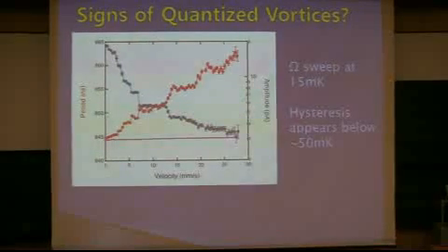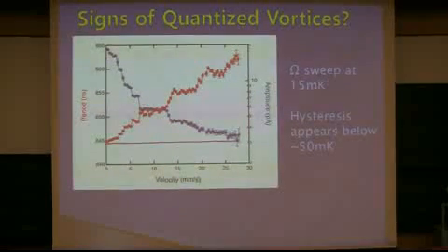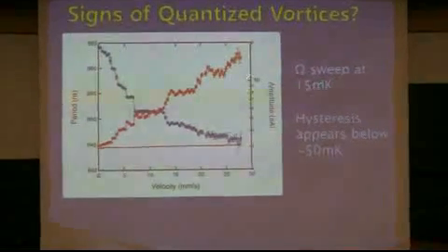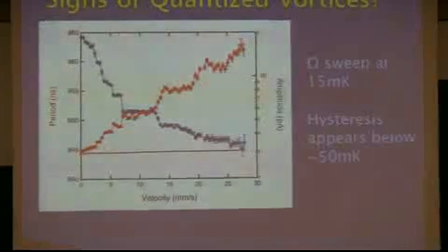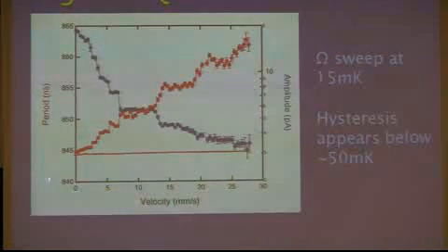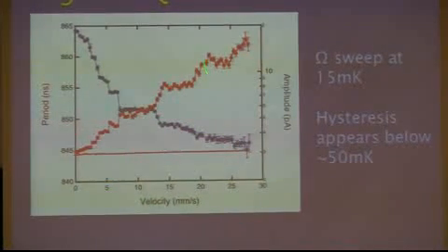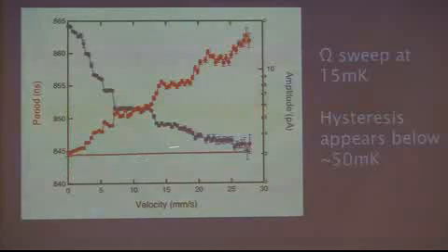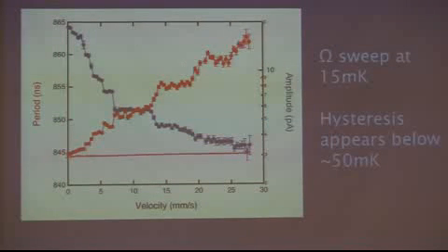Another very interesting feature. We set the temperature at 15 millikelvin and decrease the DC rotation speed continuously to 0 and then increase back again. The red one is the resonant period. The reduction in the resonant period, as I told you, corresponds to the non-classical rotational inertia. So when you decrease the DC rotation, there is an increase in the non-classical rotational inertia. The blue one is amplitude.